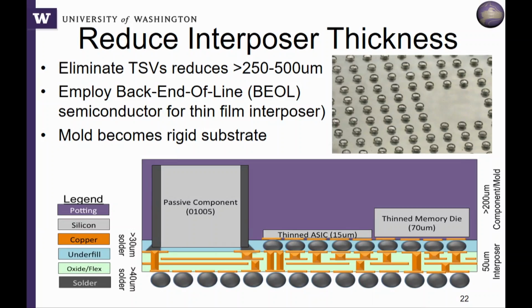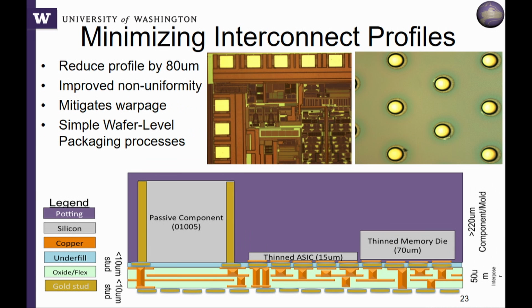Even though we managed to work out all the bugs, the next layer of thickness there was we had about 75 to 100 microns of thickness consumed by these solder balls. And so we were able to replace solder balls by introducing a standard process called ENIG. I see one of our audience members is from a company working on new ENIG technologies. We were able to remove the solder balls and replace them instead with a thin layer of nickel and then a flashing of gold, and then working on surface chemistries and surface enhancement in order to bond gold-to-gold interfaces together and remove the solder ball entirely.